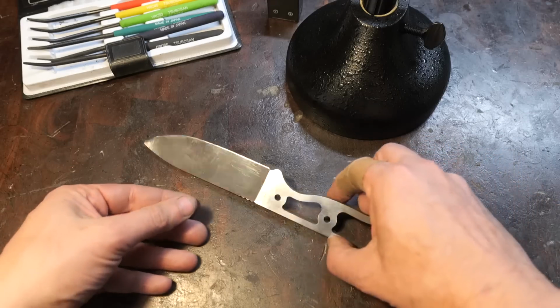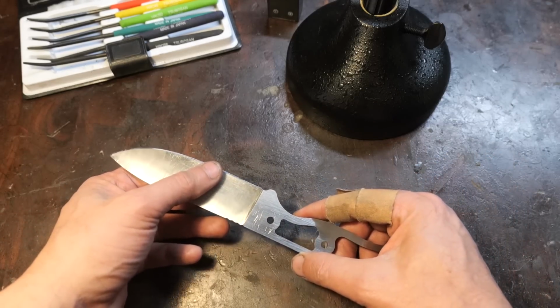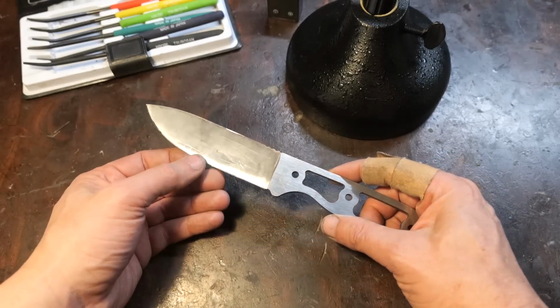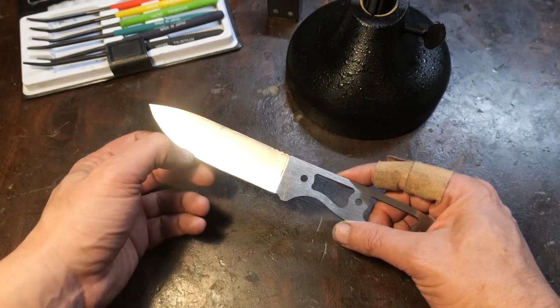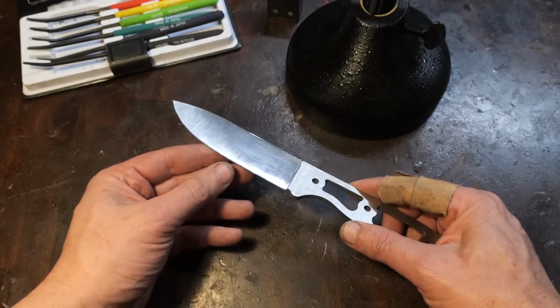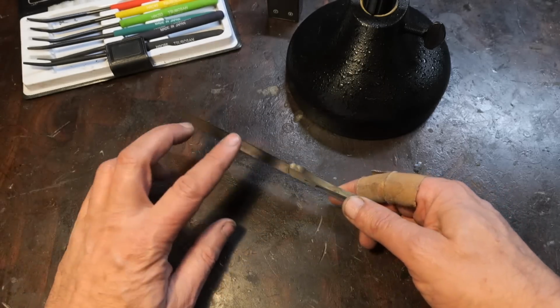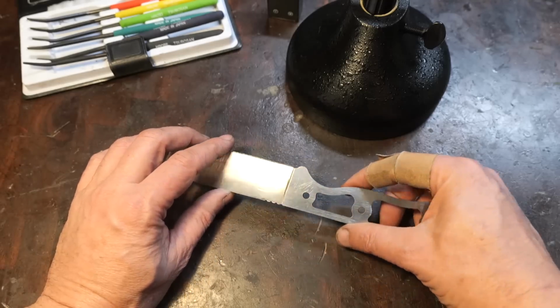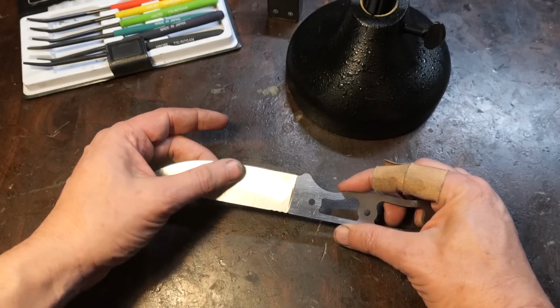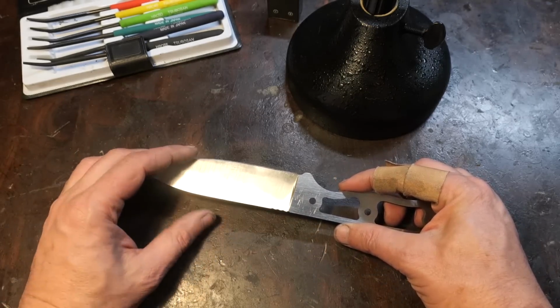It came with a thick geometry, a chopping geometry that didn't match the knife size at all, so he made it about 15 thou right behind the edge, and much thinner than the original. We put on a 17-degree per side angle, 34 all inclusive, much narrower than the 40-degree angle it came with, 19 and 21 per side.